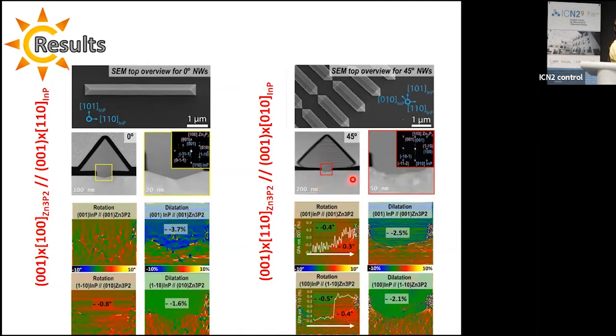Thanks to this low size of growth, the material is able to adapt on the substrate, preventing the formation of mismatch dislocation, which would create problems for the crystal quality and therefore the application.